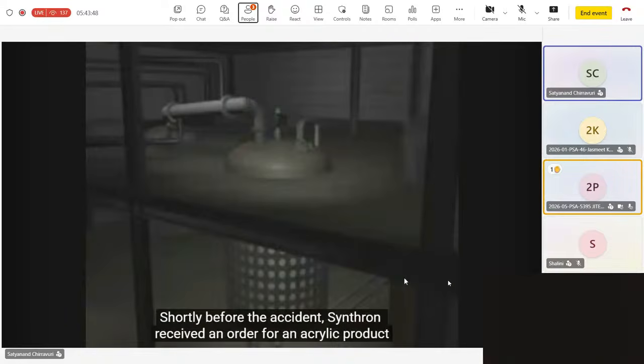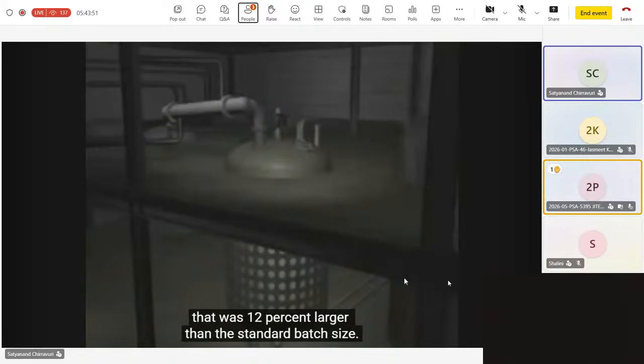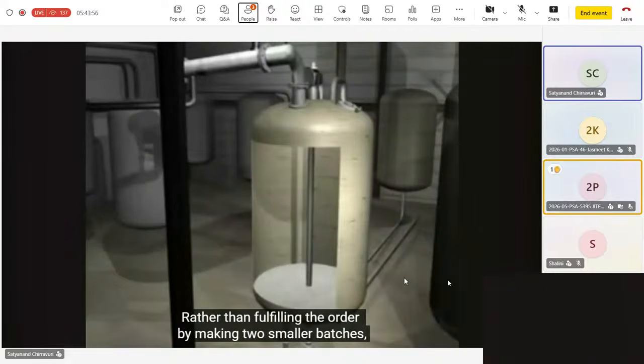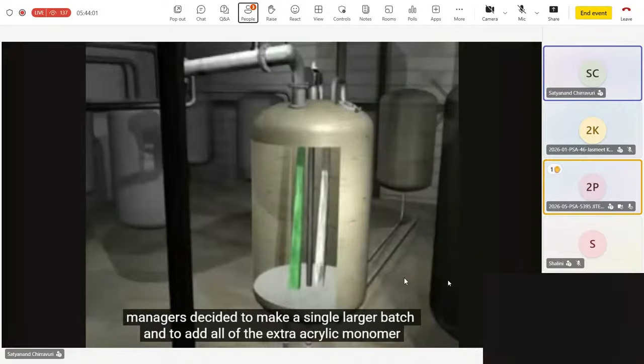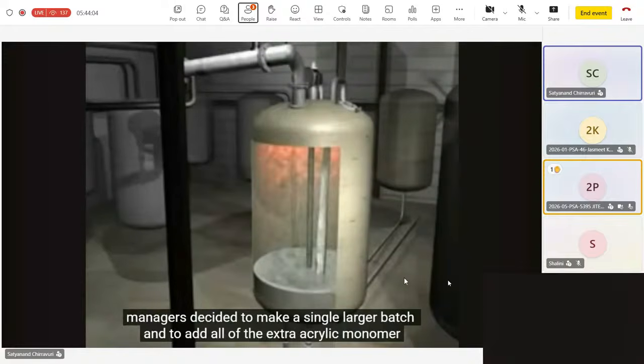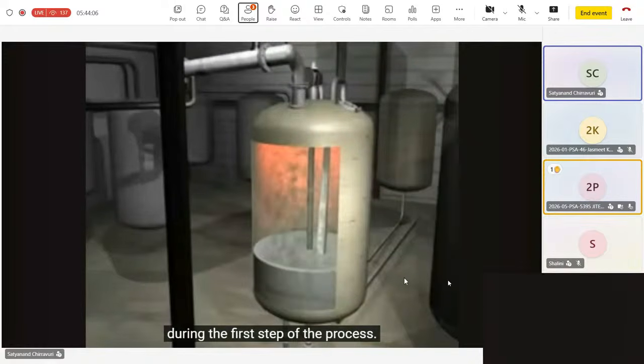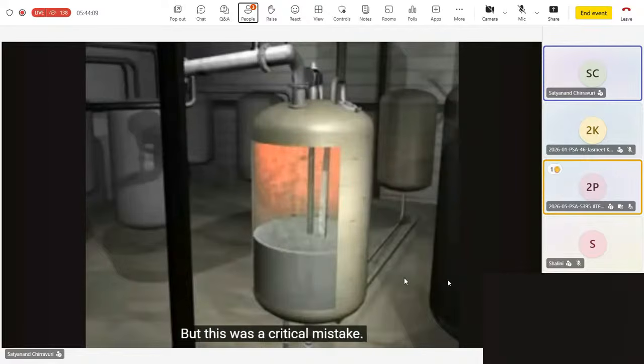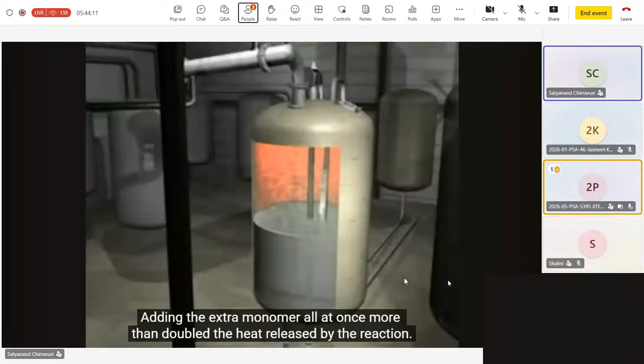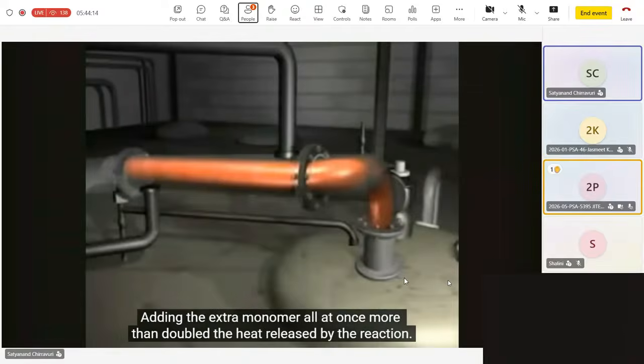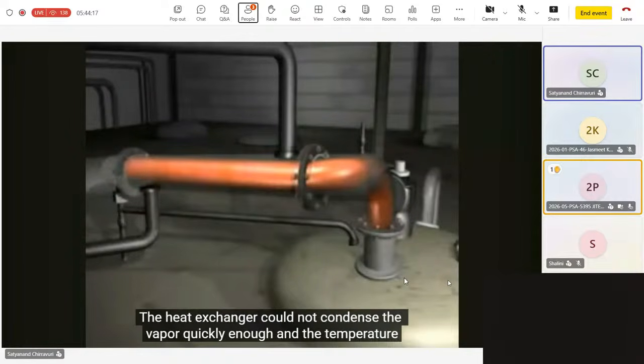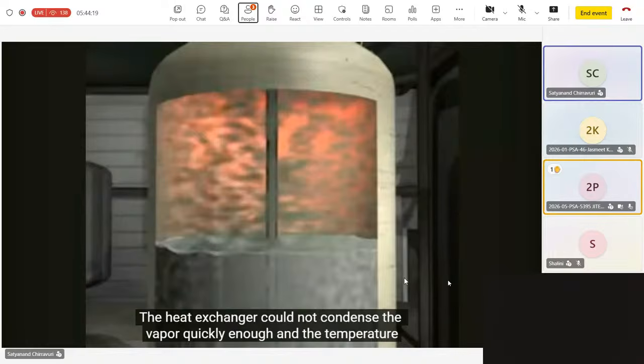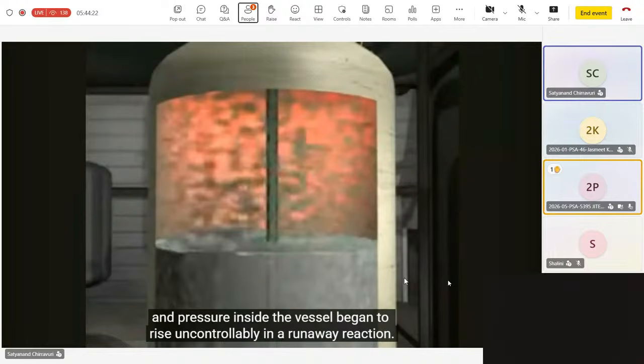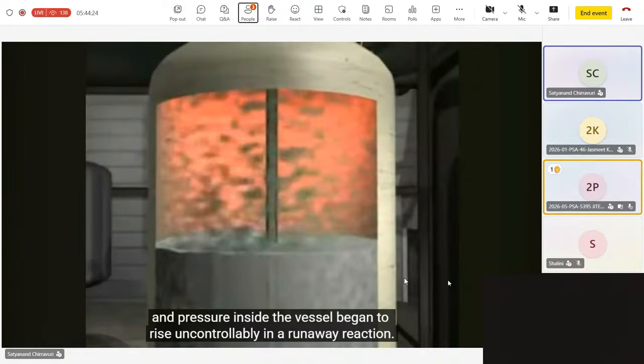Shortly before the accident, Synthron received an order for an acrylic product that was 12% larger than the standard batch size. Rather than fulfilling the order by making two smaller batches, managers decided to make a single larger batch and to add all of the extra acrylic monomer during the first step of the process. But this was a critical mistake. Adding the extra monomer all at once more than doubled the heat released by the reaction. The heat exchanger could not condense the vapor quickly enough, and the temperature and pressure inside the vessel began to rise uncontrollably in a runaway reaction.